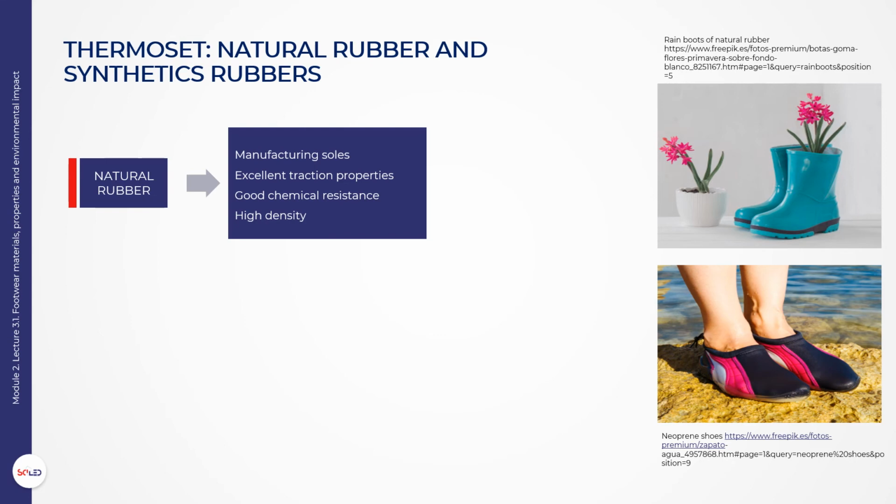On the other hand, this material also has drawbacks, such as weakness with respect to oil solvents, and in general its high density. To solve these problems, modifications such as blown gum or carbon rubber have been investigated, with their own new problems. The former decreases density but also durability, and carbon rubber is lighter and the most durable type of rubber, but limited in colors. Natural rubber has been mixed with other materials to improve specific properties: HSR, high styrene rubber, for high abrasion resistance, and EVA for low density and greater flex resistance.